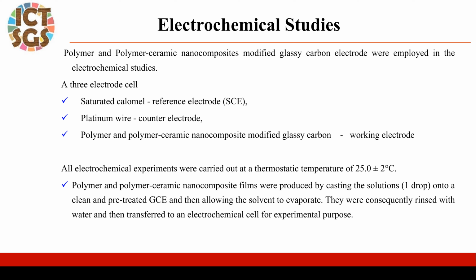Electrochemical studies. Polymer and polymer metal oxide nanocomposite modified glassy carbon electrodes were employed in the electrochemical studies. A three electrode cell was used: saturated calomel electrode, platinum wire, and polymer metal oxide modified glassy carbon electrode as the working electrode. All electrochemical experiments were carried out at a thermostatic temperature of 27 degrees Celsius. Polymer and polymer ceramic nanocomposite films were produced by casting one drop of the solutions onto a clean and pre-treated GCE and then allowing the solvent to evaporate. They were subsequently rinsed with water and then transferred to an electrochemical cell for experimental purposes.